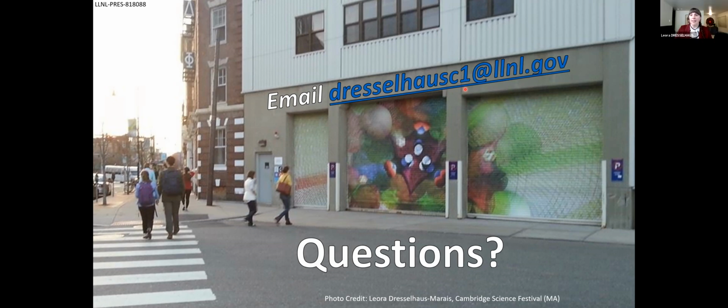What I would add to that is, as we've started to explore different applications of DFXM, one thing that has become clear, especially with the time resolved variant, is that sometimes sensitivity doesn't really help you, especially in high deformation content materials. So this is a place where a pink beam might be helpful to see some intensity in more highly deformed structures so that you can start to tease out those dynamics. But this is a longer discussion than a quick comment.